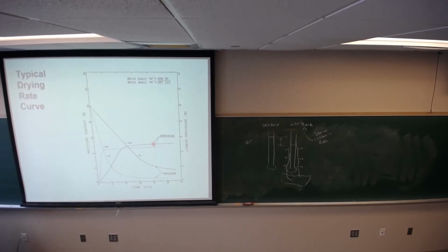What happens is the outside dries, and the inside remains sort of the jelly center thing, and you don't get as much shrinkage out of the system. If you slow that drying process down, so the solid lines are 50% relative humidity at 50 degrees C, that's still hot, okay, but you have more humidity in the air. That slows down the evaporation rate, and you get more uniform shrinkage. And the argument that's brought up all the time is that if you dry too fast, the body cracks. Correct? Also, lots of arguments for warping, which is possible, but that's very rare for us to see. Only in very specific conditions do you see that.